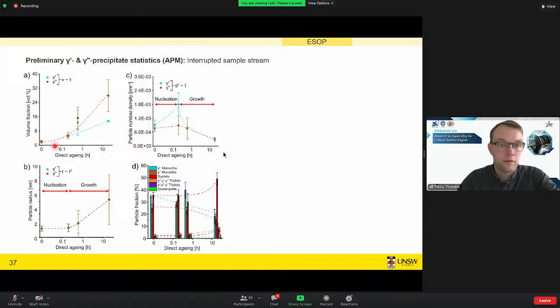So does it mean that if you prolong this material for long heat treatment, like 1000 hours in service, the volume fraction will change? Also, DO22 is much higher than L12 structure. So does it mean that DO22 is more stable than L12 structure? The second question: I would like to know if there is a mechanism of the transition from L12 structure to DO22. That is the second question.